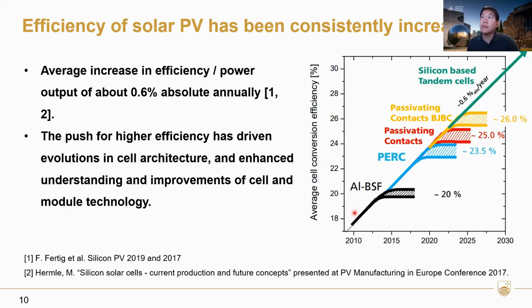But although this trend has been quite steady, the improvement in efficiency has actually gone through a few cycles, from the very early cell structure based on aluminum BSF, transitioning to PERC when the efficiency of the aluminum BSF reached its maximum, around 20%. And now we are heading towards the end of the PERC cycle. PERC is the dominant cell technology right now. We're heading towards passivating contacts over the next few years. And part of the improvement in efficiency, in addition to cell architecture, of course, is also better understanding and improvement of the cell and module technology that's involved, every part of it.